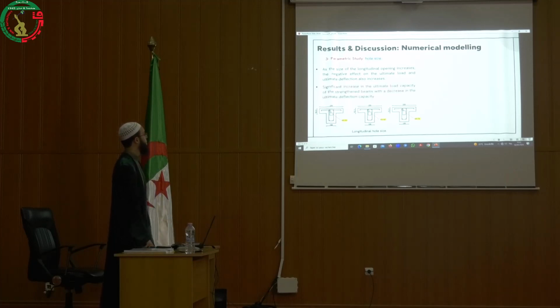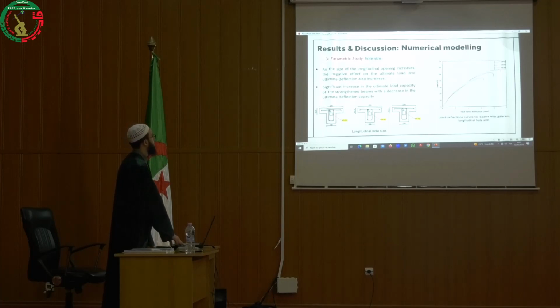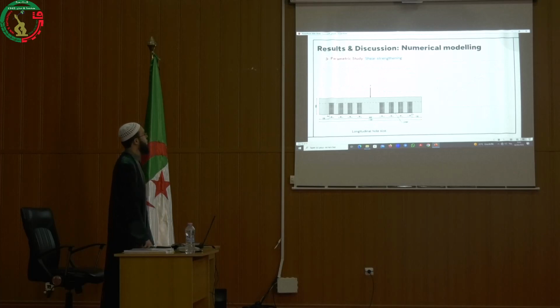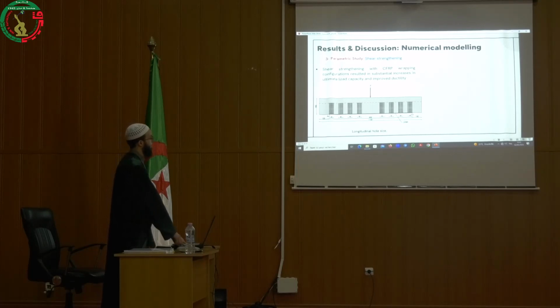After strengthening the beam by CFRP laminate on the tension zone, a significant increase in the ultimate load capacity of the strengthened beams was observed, as you can see in the following curves. To avoid a premature debonding, we employed shear strengthening. The shear strengthening with CFRP wrapping configuration resulted in an increase in ultimate load capacity and improved ductility, as you can see in the following pictures.